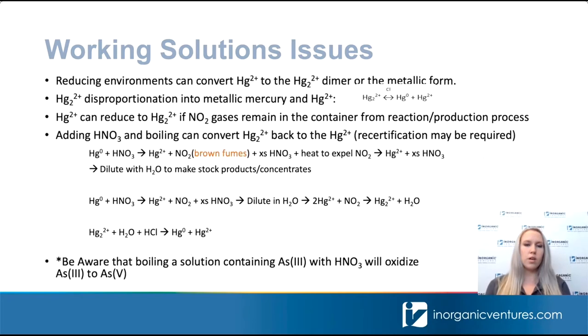We discussed briefly earlier in the presentation that reducing environments can convert mercury ions to the dimer form. To ensure that you don't have any dimer species present in your concentrate prior to adding chloride, you do need to convert the dimer back to mercury 2 plus ions. To do this, you can boil with excess nitric acid, and this will convert all of the dimer back to mercury 2 plus. However, be aware that recertification may be required for the new concentrate to ensure that the concentration of mercury has not been affected. Another thing to be aware of is that any arsenic 3 contained in the solution will be oxidized to arsenic 5 when boiled with nitric acid.